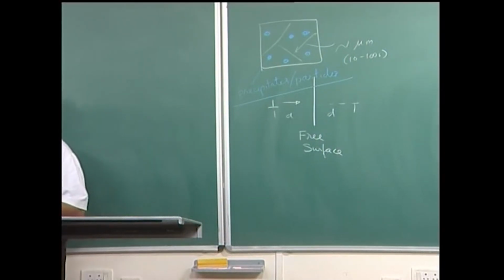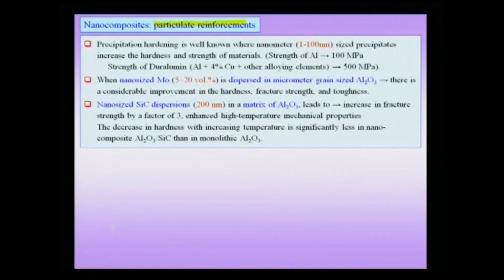And this nanoscale dispersion of the second phase in a bulk first phase can actually give rise to a tremendous increase in strength, as shown in some of these examples here. We have already of course talked in detail about the precipitation hardening system, wherein you have precipitates of the scale of 1 to about 100 nanometers, and we will not repeat it here, but which is the case of the duralumin, which is a precipitation hardening system.